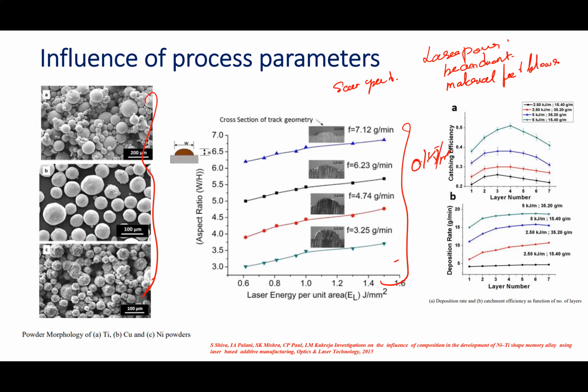It was also observed that the various outputs in the cross section of the track geometry were obtained with different combinations of laser energy and the powder fed per unit area. So basically this shows the track geometry in the prescribed form of the aspect ratio, with respect to the ratio of the width and the height of the track.